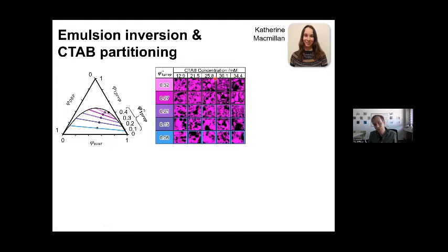So what she does, she prepares, again, like Azim, equilibrium immiscible mixtures of oil and water, and then she does that at a specific concentration of the surfactant and the particles, and she just then vigorously agitates it, and she sees, is it a water-in-oil or an oil-in-water emulsion?